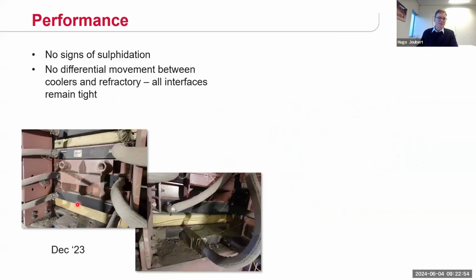So these pictures were taken December 23, so just last December. The furnace had been in operation for 14 months by then, but it looks the same today. It still looked extremely good on the outside. There's absolutely no sign of sulfidation on any of the copper coolers, and no differential movement between adjacent coolers and between the coolers and the refractory lining below.